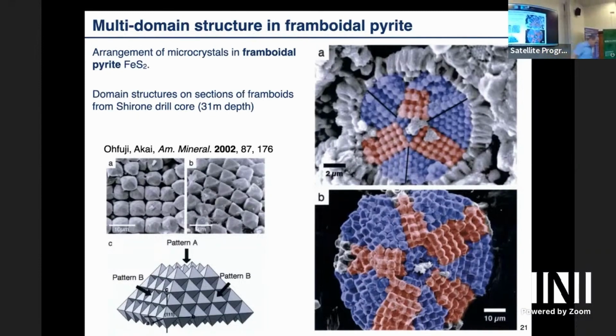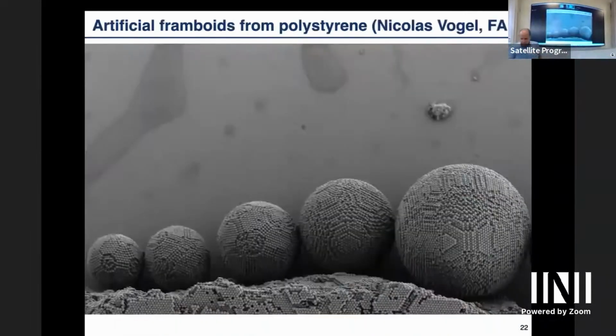And what fascinated me here is that it also forms some symmetry. So not only do they form the clusters, but the clusters themselves order. But there's still a hierarchy. These particles are crystalline, single crystals, and then they form this polycrystalline sample. So here, iron sulfide is the chemical compound. This is from Japan. They just take this out of the ground from the drill core, and it's just found like this.